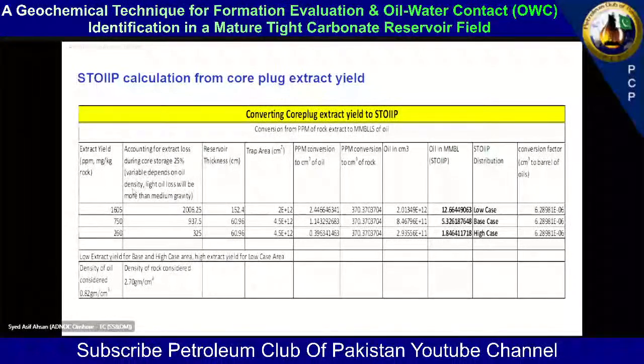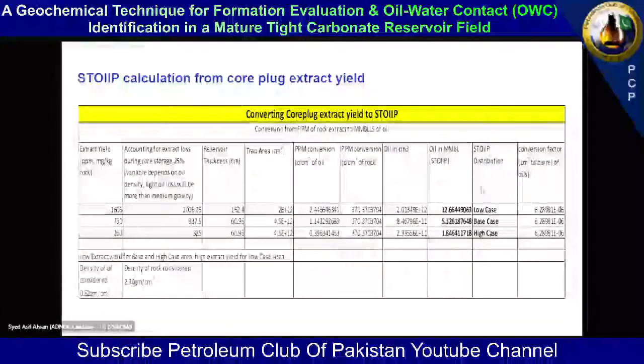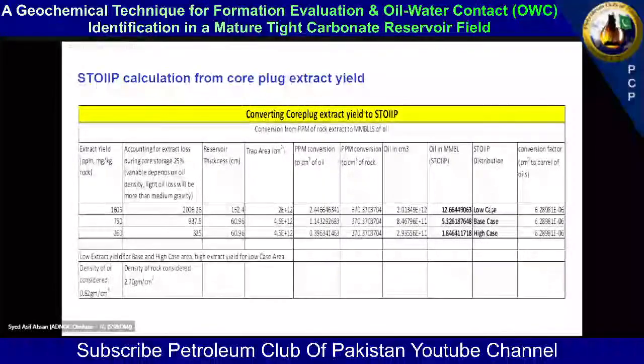And I know the reservoir thickness, I know the trap area, and ppm, parts per million, of the extract yield. I have converted that into centimeter cube of oil per centimeter cube of rock using this factor, and I got the oil volume in centimeter cube. And I've converted this into oil in millions of barrels using the conversion factor, and this is the STOIP distribution in the low case, base case, and high case. So a low case plus base case will have about 18 million barrels of oil.